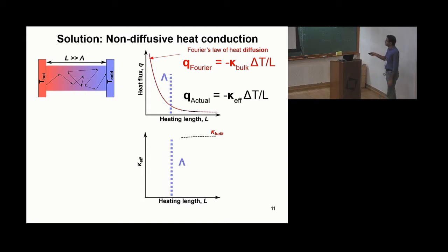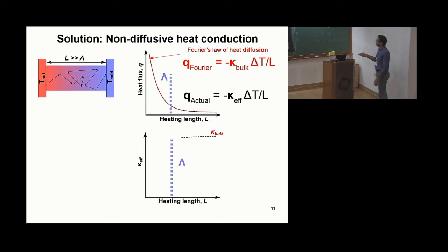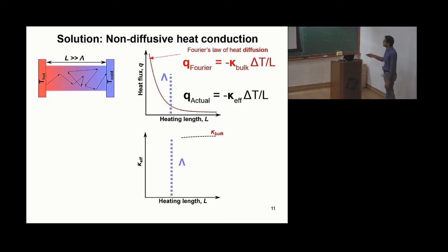In this case, the heat flux that you typically measure in an experiment is actually consistent with what Fourier's law predicts. I'm trying to draw a dashed black line over this red curve, and up to this point, the heat flux measured in the experiment agrees with Fourier's law's prediction. Lambda is the mean free path of all phonons in the material.